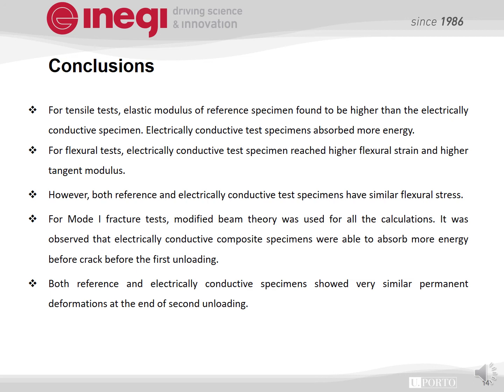For the Mode 1 fracture test, modified beam theory was used for all the calculations, and it was observed that electrically conductive composite specimens were able to absorb more energy before the crack jump, which was before the first unloading. Both reference and electrically conductive specimens showed similar permanent deformation at the end of the second loading and unloading. Different experimental values like compliance, energy release rate, and modulus values were very similar for both reference and electrically conductive specimens, and they were calculated from this modified beam theory as well.